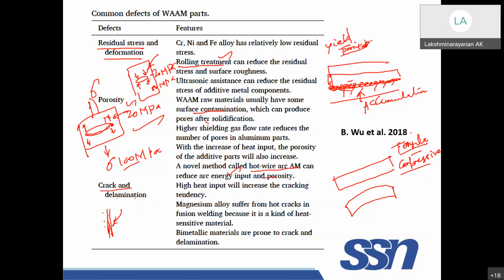Crack and delamination are one of the problematic things, especially when heat input is increased. When you increase the heat input, as I told you, accumulation of heat will sometimes lead to cracks. Cracks also form when you mix two different metals, which have different physical properties. Suppose I provide aluminum from one side and steel from another side. When I melt both, these two are not a compatible system, especially in the liquid state, so naturally cracks will form. There are some mechanisms, don't worry right now. Similarly, magnesium suffers from hot cracks. Even aluminium also suffers from hot cracks.